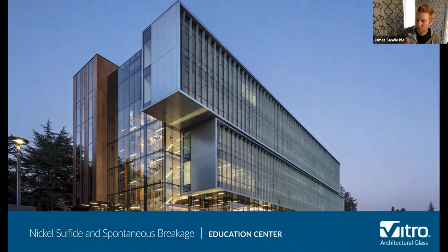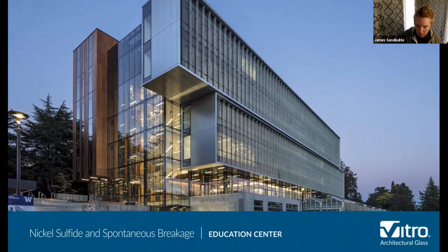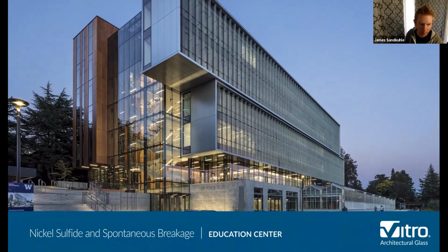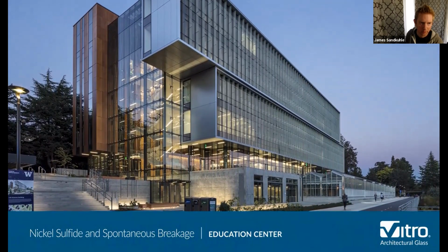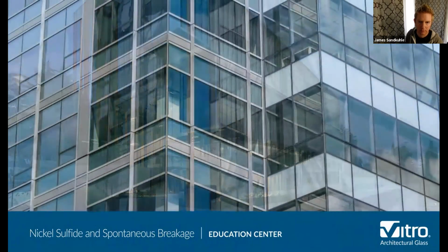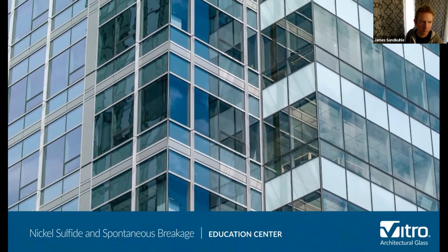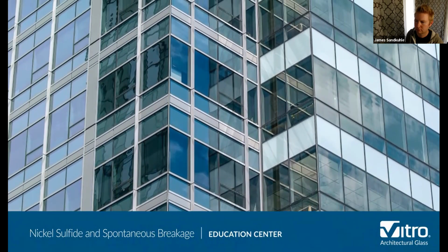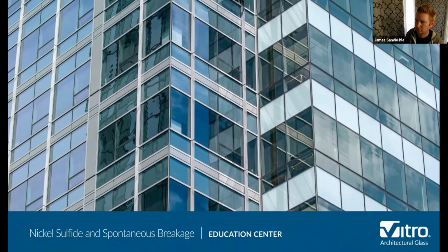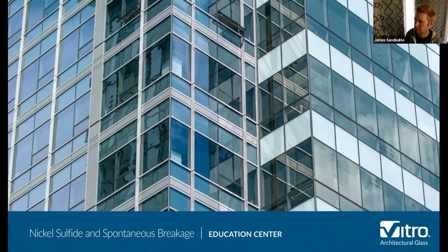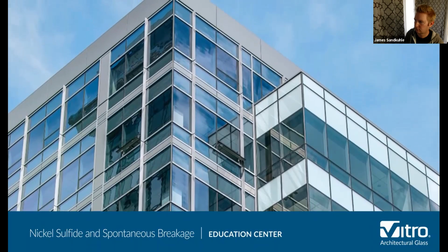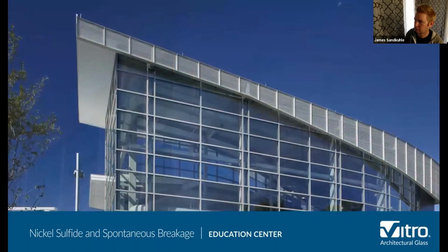When you think of some of the world's most dramatic buildings, they most likely involve large expanses of glass. However, large expanses of glass may be prone to spontaneous breakage, that is, breaking without any obvious cause. When this occurs, it could be due to glass edge or surface damage from handling and glazing. Building or framing system movement, as well as vandalism, are also common causes. However, today we will discuss a specific type of inclusion, nickel sulfide stones, that can also cause spontaneous breakage.